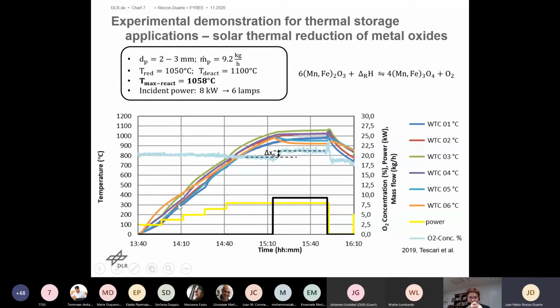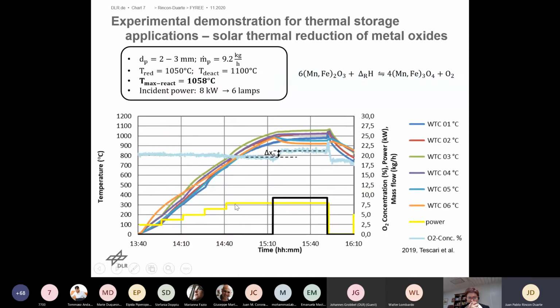Here in this graph, we can see the signals of the thermocouples inside the crucible, which are these colorful lines. And on the right side, we have the signals of the oxygen sensor that we have for the gas flow, as well as this black line, which is the mass flow. So we started the experiments turning on the lamps step by step in order to avoid a thermal shock on the crucible. After we reached the reaction temperature, we started the feeding of the material, which is this black line here. And some minutes later, we reached steady state conditions with the reactor.